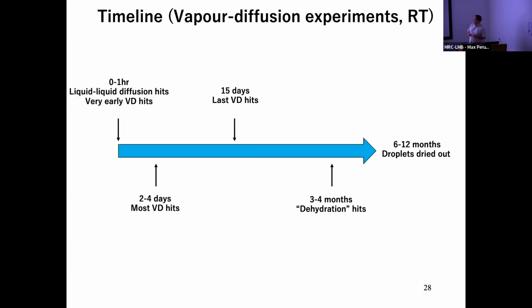After that, it's a bit more vague. So after months, depending also on the quality of the plate and the quality of the seal, the MRC plate with the seal we use is very good at that. The dehydration is not occurring before months and months. But let's say after 3-4 months, you have what I call eventually the dehydration hits. So now you're not looking at what's happening with the vapor diffusion experiment, but with the overall dehydration of the plates. So you further increase the concentration.